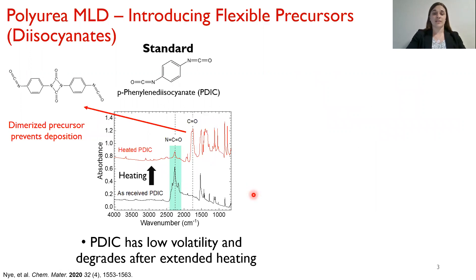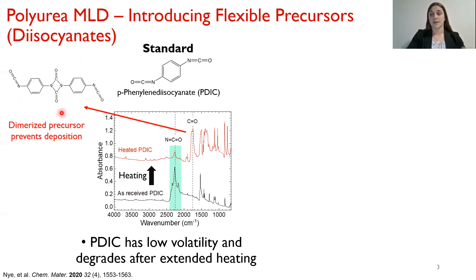We analyzed the thermal stability of this material after extended heating, like what you would see on an actual reactor. We find that after heating, this undergoes thermal degradation via dimerization, which you can see from this FTIR plot by the disappearance of this highlighted isocyanate peak, which disappears after a few months of heating. Instead, we form a carbonyl peak, and this chemical transition is indicative of dimerization. This dimer — this larger molecule — is not capable of being dosed into the reactor and not capable of an MLD reaction. Thus, it would be beneficial to have a more thermally stable alternative to use as the diisocyanate.